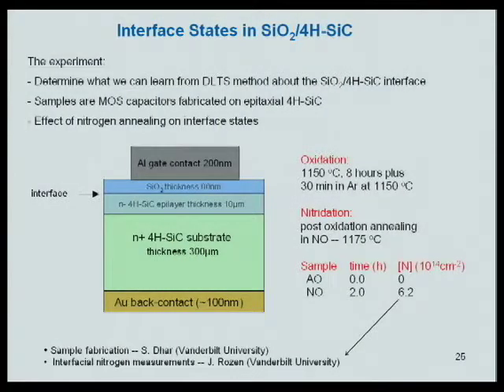But we don't understand this process. We still don't really know what the defects are. We still don't really know what's going on at this interface. So our group got involved in this project, and the idea was to use deep level transient spectroscopy to see if we could get additional information about these defects. The samples we're looking at consist of a very high quality epitaxial silicon carbide layer, a thin oxide layer, and some metal contacts. We looked at samples after oxidation, and then some were further exposed to NO at high temperature.